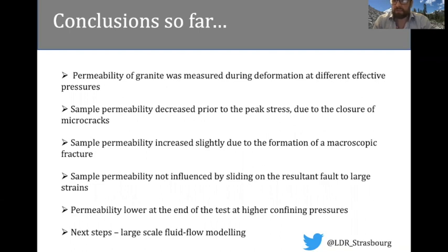And finally, we've seen that sliding on the macroscopic fracture to very large strains does not appreciably change the permeability of the sample. And so qualitatively, the permeability evolution from the three samples was very similar. Quantitatively, we see that the permeability of the sample at the end of the experiment is higher at lower effective pressures or depths. So these are the conclusions so far from this experimental study.